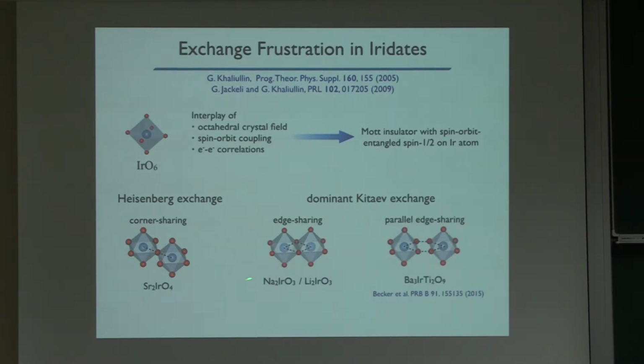So one interesting is this edge sharing arrangement or parallel edge sharing arrangement. And the important feature here is that you have two exchange paths. So this iridium atom is connected to this one by this upper path and by the lower path. And these two exchange paths, they interfere destructively, which basically kills your Heisenberg interaction. And the interaction that is left is the Kitaev interaction. Khaliullin and Jackeli, they didn't just explain that this arrangement could give you a dominant Kitaev interaction, but they actually